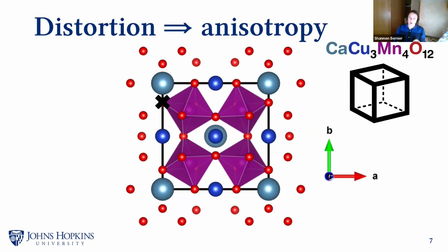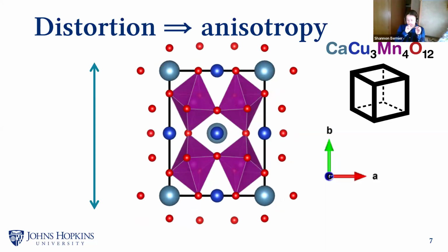But if I go through a quote-unquote pseudo-cubic transition, and I make this a nearly cubic but not quite cubic shape by stretching it along one axis, now what we call the apical oxygens, the ones at the top and the bottom of the polyhedron, are further away. They have a weaker electrostatic interaction with the central atom, and therefore it's most likely that one of those is going to be the one to go. So this is why pseudo-cubic transitions can be important. It's why the word can have really important meanings, but as I've mentioned, it's not rigorously defined.